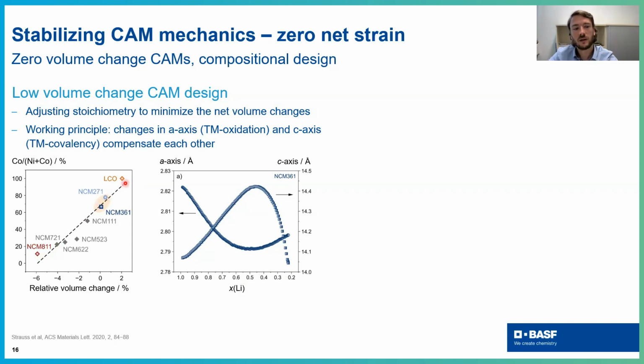And now in this line, you can spot a point where you essentially have zero volume change. And this is a nice work done by Florian Strauss. And I think this idea was from Pascal Hartmann, essentially, where you are making such a material, which was really synthesized, to achieve zero volume changes in the solid state battery. And how do we do that? Well, you know that these materials have two crystallographic axes, and one axis shrinks during the charge and another expands, and you can tune them in the way that they are just compensating each other.